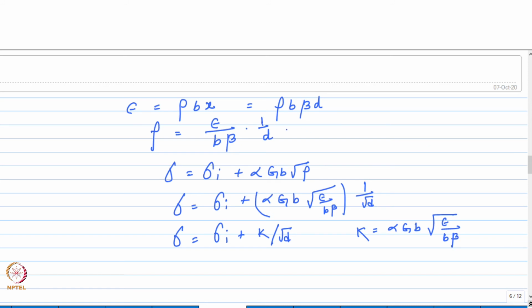And from here you can also see that the dislocation density increases proportionally with the strain, and this is quite obvious as we have discussed while discussing about the work hardening or the cold working. As you deform the material and provide more and more strain, the dislocation density would increase, and as a result of that the strength will also increase. So that fact can be also seen from this theory, which again goes by the dislocation density with regard to the strength of a material and the grain size.